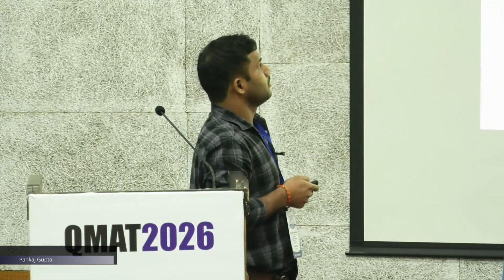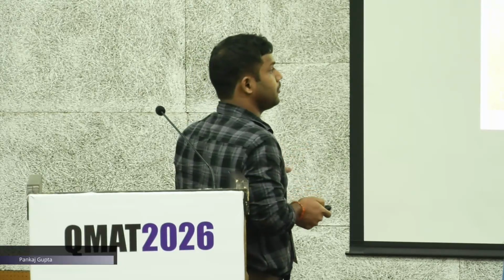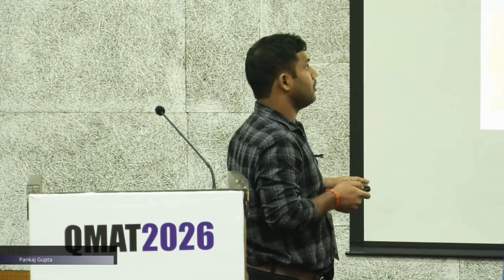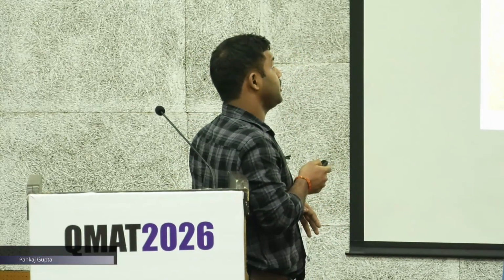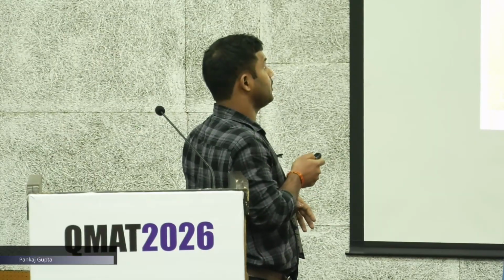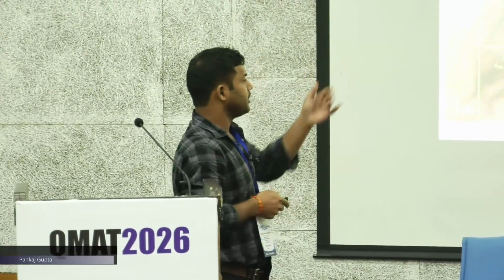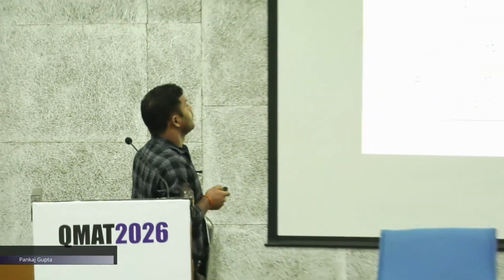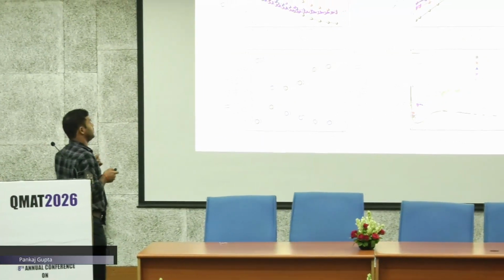So for this purpose we prepared a large series of samples, and we found the XRD is very clean. All samples are single phase, following Vegard's law because of the lower atomic size of antimony and silver. There is lots of lattice disorder as expected, because there are lots of different atoms present in the system, that is bringing lots of lattice disorder. That is helpful for reducing the thermal conductivity.